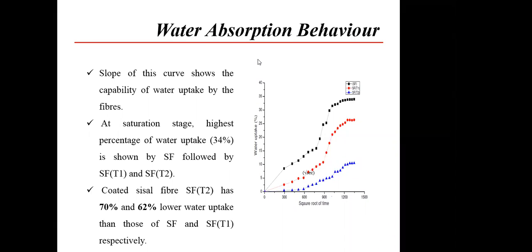The slope of the curve shows the capability of water uptake by the fibers. The highest water absorption takes place, you can say near about 34%, by untreated sisal fibers. Before modification, before surface treatment, there is 34% water uptake by the untreated sisal fiber.